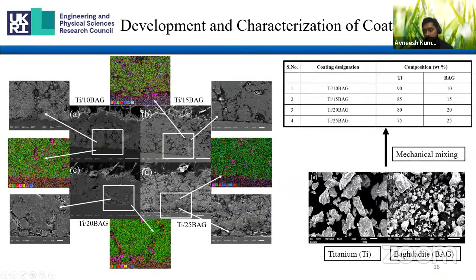And then we sprayed these titanium and baghdadite particles using the cold spray facility. Depositing baghdadite is difficult, because baghdadite is ceramic in nature, as we have seen previously in the bonding mechanism of ceramic particles. So for that, we need a metallic material, and we use titanium, which has good biocompatibility and a good strength to weight ratio. We mixed these powder particles in different ratios. Here is the coating designation we are going to use throughout: 10 represents 10 percent baghdadite, and 15 represents 15 percent baghdadite. In this ratio, we mixed the powder particles mechanically and sprayed onto the SS316 substrate.